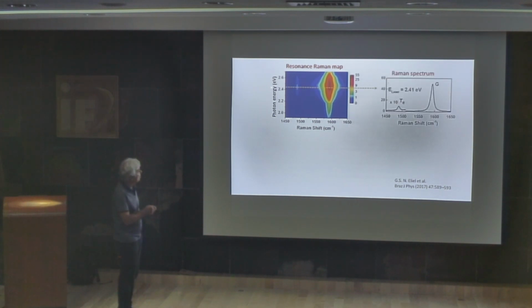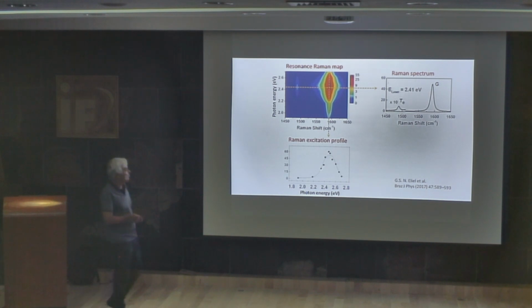If I take only one energy, for example, the green laser, then I have the Raman spectrum. Here I will show the Raman spectrum of graphene. This is the G band, and this is another band that we call the D band. But if I fix one peak and follow how its intensity changes when I change the laser energy, something like that, then what I'm drawing here is the Raman excitation profile. The Raman excitation profile is the intensity of this band, the G band, when I change the laser energy. You can see the band becomes very intense, and after that becomes weak.